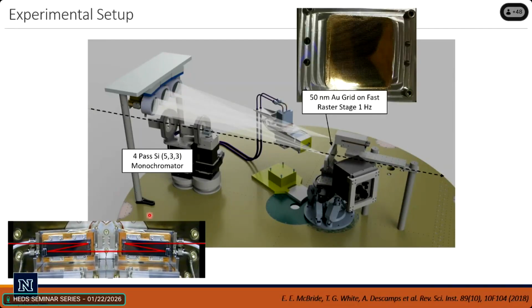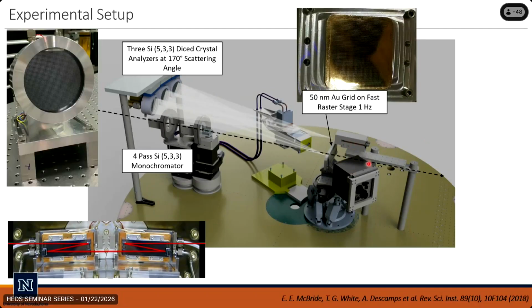Then the X-rays come in and they scatter off the target. In this case, we've been using 50 nanometer gold, so very, very thin gold. And that's because we're able to heat it with a short pulse laser very uniformly, so that's why we keep it so thin. We've also done this experiment now on methane, 50 micron methane, and on thick micron size shock targets too. But we started with just very, very thin gold. It doesn't scatter much because even though it's gold, so it's heavy, so it scatters a lot, it's also ridiculously thin. So if you're keeping track, we're losing a lot of X-rays when we go through this monochromator right here. We're losing some X-rays because we have a very thin target.